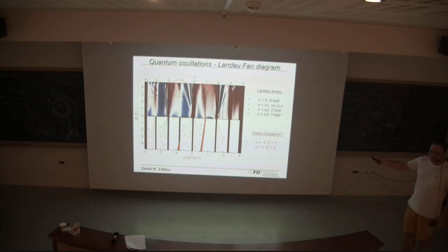Okay, so that being said, now I'm probably getting a little bit off my comfort zone. Towards the end of the talk, I just want to talk about things which are not very clear right now. We also observe, for example, at the 1 and -1 insulating states, features which don't show any Shubnikov-de Haas oscillations, so we don't think we see any Landau levels, but somehow the insulator itself seems to change its position in a linear fashion depending on dn over dB, and if we look at the carriers which go into these states, we can assign a filling of 2 to this slope here. And here in the corner we also see a slope which we can assign a filling of 1.